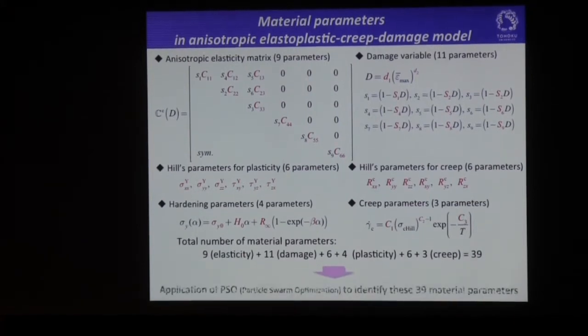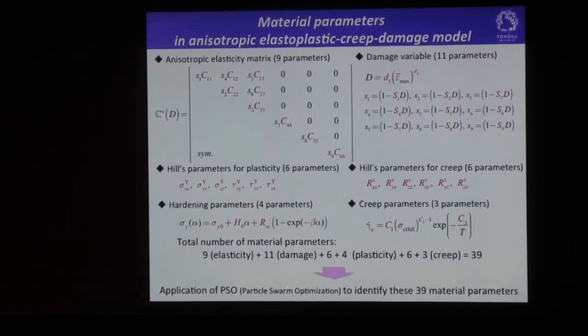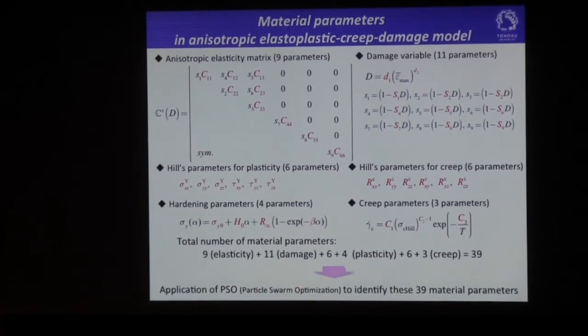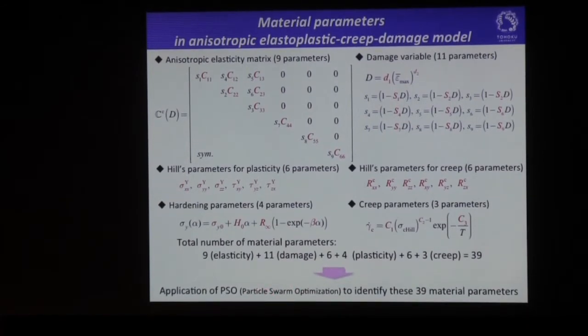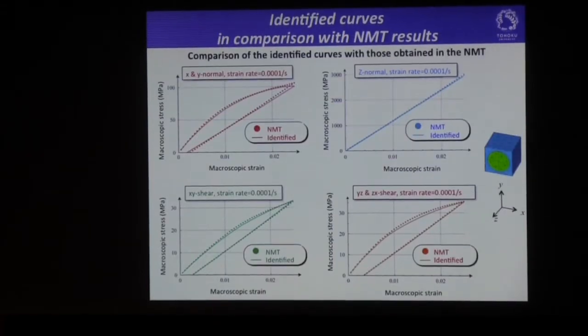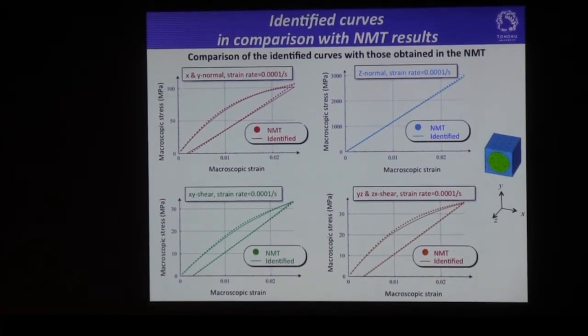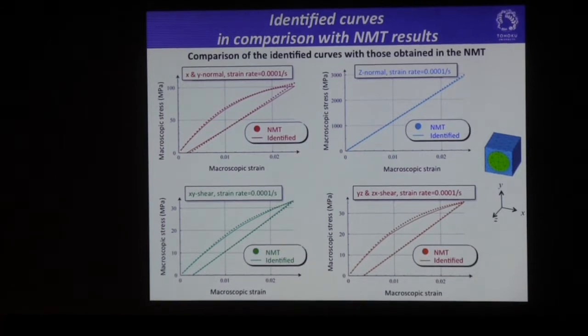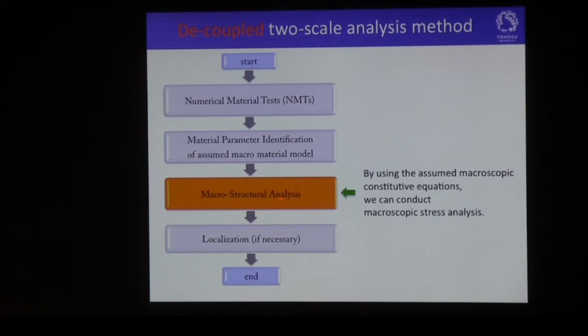In this study, I applied the particle swarm optimization, which is one of the population-based descent methods. Then we applied this method to identify these 39 parameters. We could obtain this kind of identified curves in comparison with the numerical material results. As you can see, the identification is quite successful. So we can move on to the macroscale analysis.